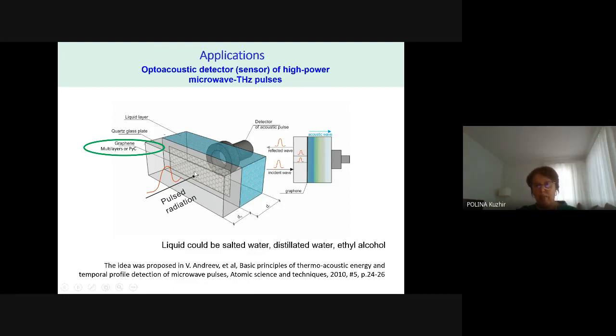First, the radiation comes from the window side. It will be absorbed in the graphene layer, which leads to heating via the Joule effect, and this heating generates an acoustic wave that will be detected by a detector of acoustic pulses. There will be a time delay between the pulse and the detection of this acoustic pulse, which is very good, because there exists a terrible problem of detecting high power pulses of microwaves and terahertz.